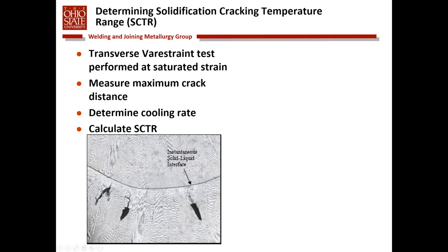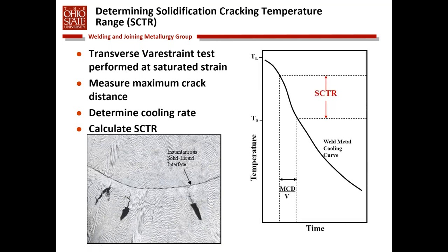And then we're simply, from a quantification standpoint, measuring the distance from this location to the back end of this crack to determine the temperature range over which solidification cracking occurs. So if we know this maximum crack distance, and we know the velocity at which we're making the weld, the rate at which this solid-liquid interface is traveling, we divide MCD by velocity, that gives us a time, and we superimpose that on the cooling curve.